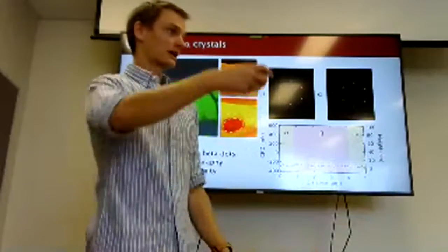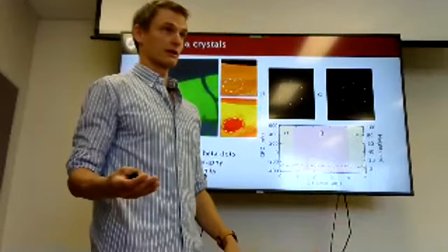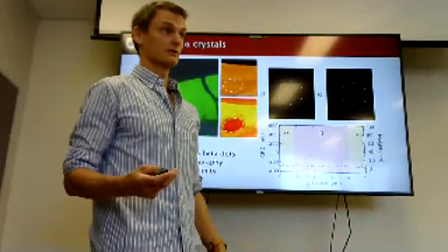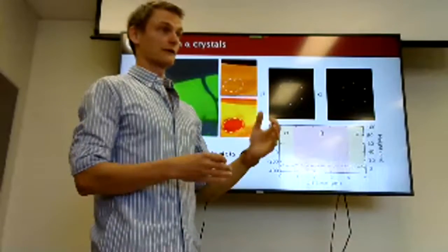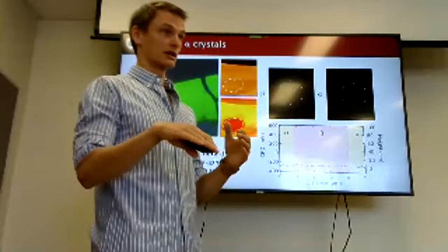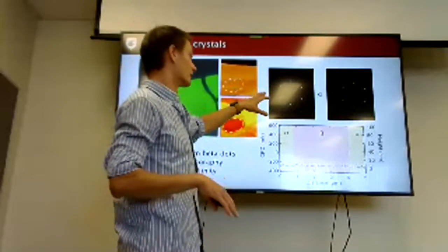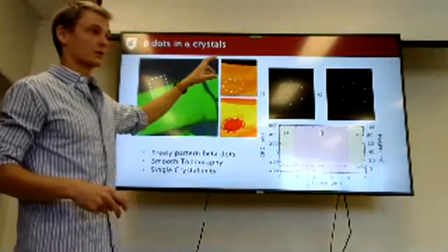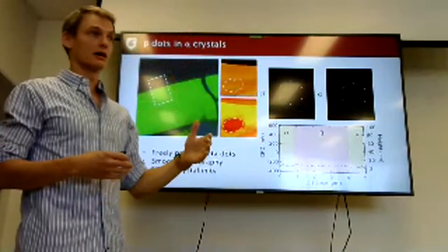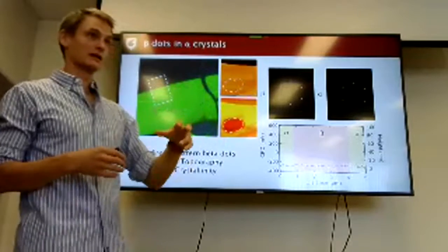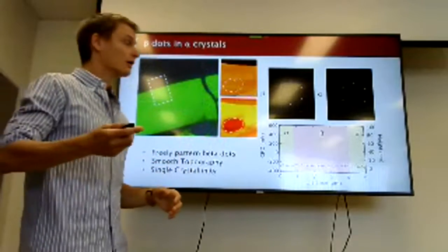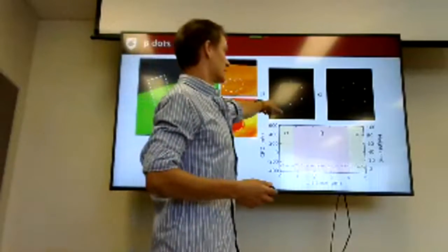Then the last thing we wanted to check is to see if we preserve the single crystallinity of the indium selenide. So in the past, we've shown that the alpha phase to beta phase does not change the orientation in plane. So that's what we're checking here with the exact same setup, but we exfoliated over a TEM membrane, and then put the polka dots in it. And Matthew did a TEM, and sure enough, we have the same crystallinity for the alpha and the beta phase.